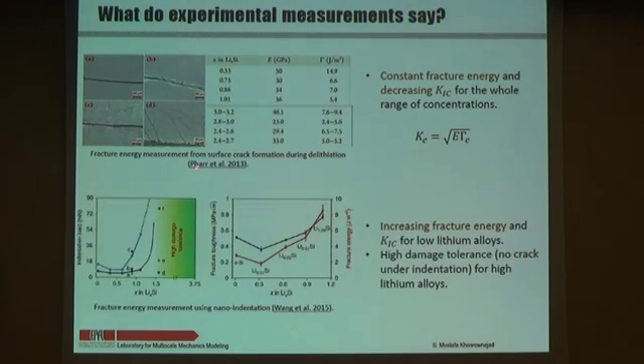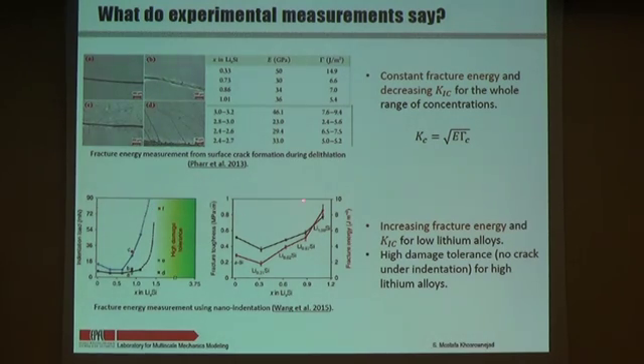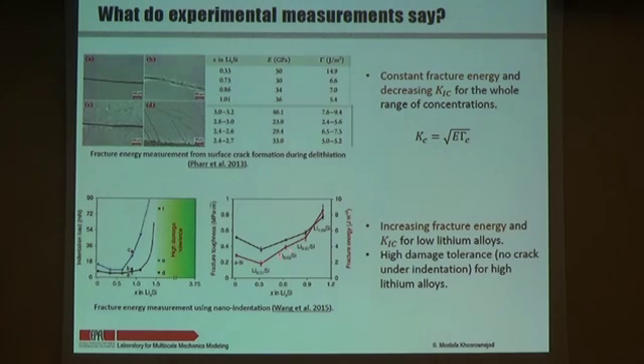There is another study which performed nano-indentation on the lithiated silicon system. They did not see any cracks starting above some lithium composition threshold — so at higher lithium content they call it a high damage tolerance system. More than that, the fracture energy actually increases with the amount of lithium, which is contradictory to the previous study. So experimentally it is not very well known how it works.